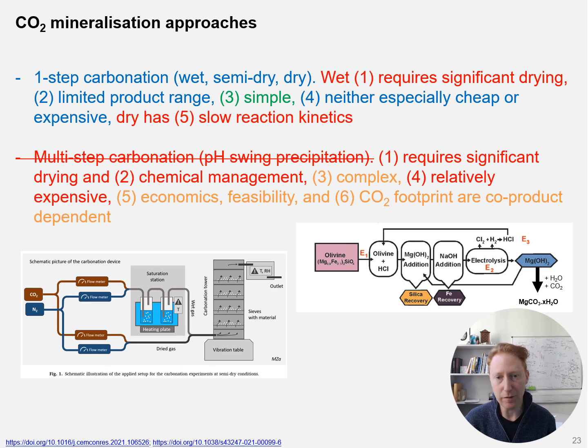So to summarize the CO₂ mineralization approaches, one-step carbonation is promising because it is simple. It is simpler than the multi-step carbonation process, but produces one product. Now, this is not a problem for the concrete value chain since, for example, it can produce carbonated recycled cement fines, which have very good potential as a supplementary cementitious material. The wet process requires significant drying, the humid process or semi-dry process requires less drying, and the dry process requires no drying, but the problem with it is that it has slow carbonation kinetics. The multi-step carbonation process requires significant drying, it requires acids and bases and chemicals management. The process is relatively more complex, relatively more expensive, and the economics, feasibility, and carbon footprint are co-product dependent.